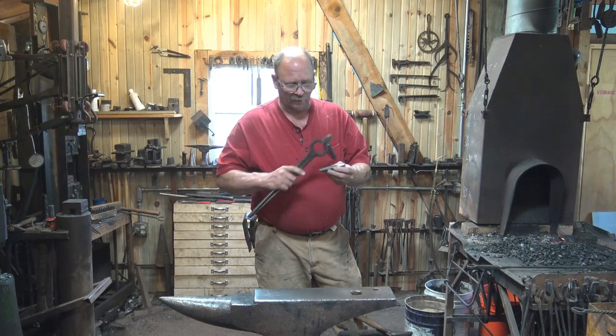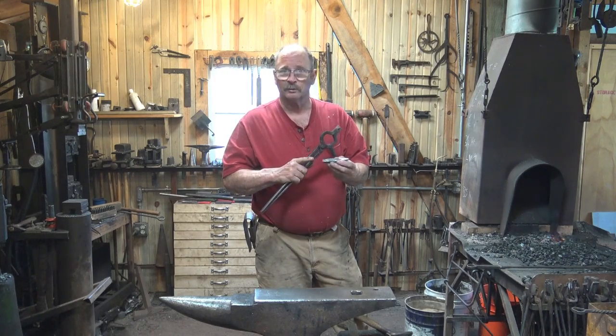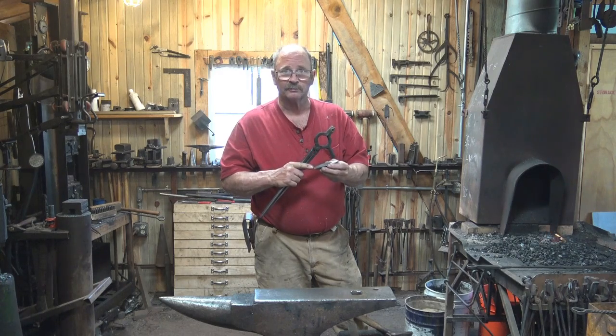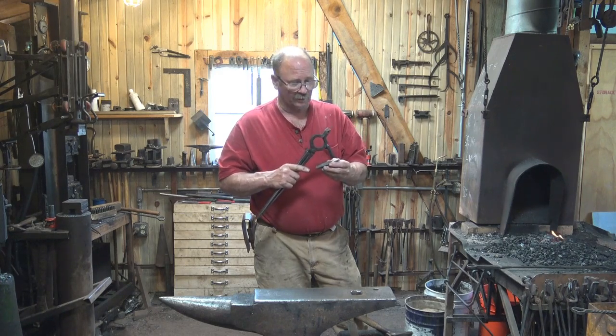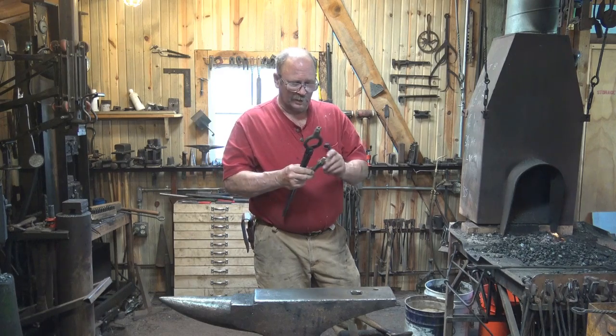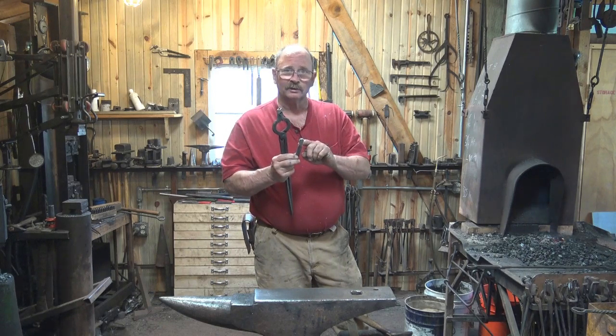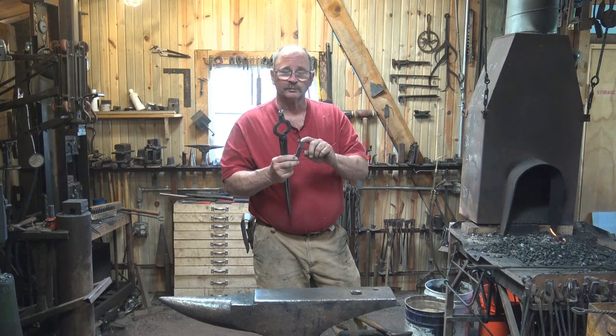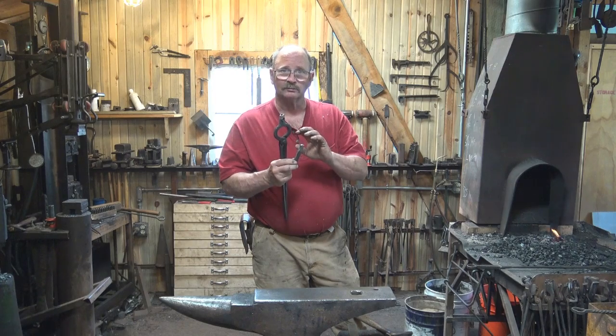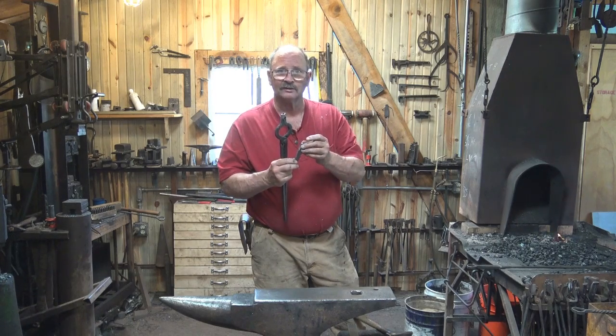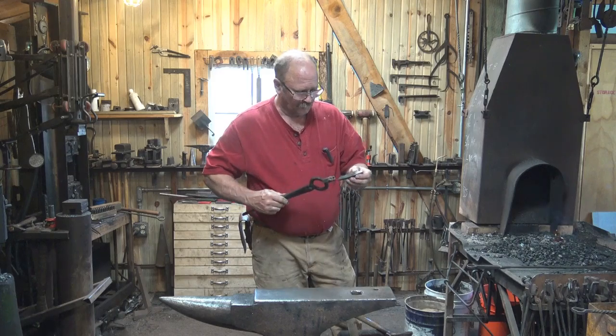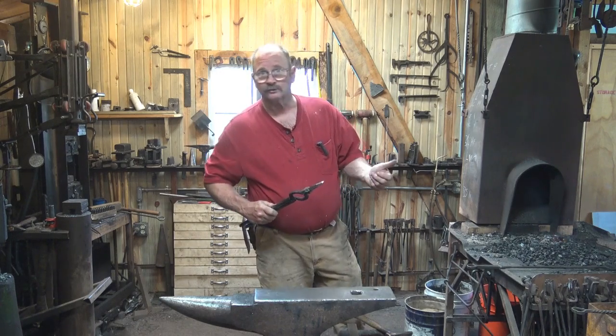Now for this, we don't need to harden the struck end. If we do, I'm going to soften it again. I'll take a torch and heat it up and draw the temper way back on that. But we need an even heat on the end that's doing the work. If you just get the surface hot, you can harden the surface, but it's going to have a soft core, and that could create stresses that will cause a crack. So you want an even heat throughout when you go to quench. And part of the way you do that is by soaking.